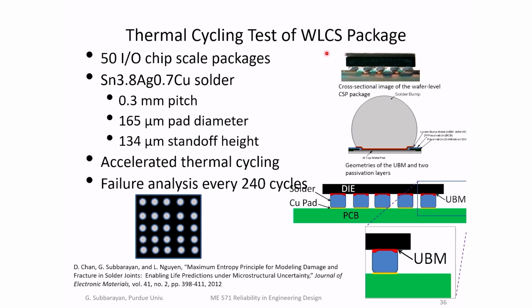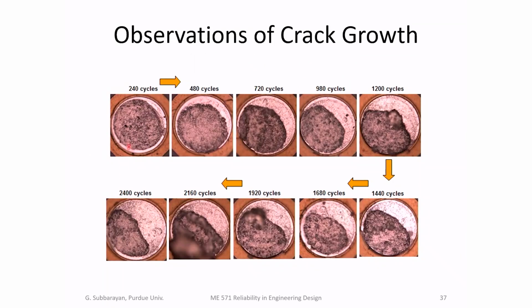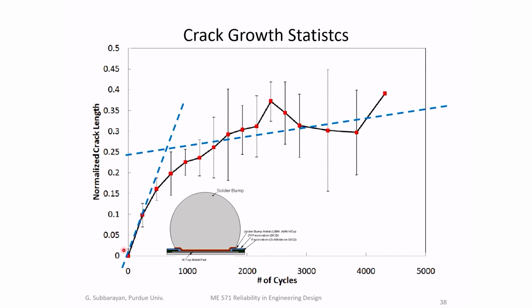So we take a wafer level chip scale package, and then we cycle them in a thermal chamber. Every 240 cycles, the test board was sent to us to do failure analysis. So we characterized how fast the cracks grew in the real sample. And this is the growth of the crack. This is how far the crack had grown at that number of cycles. You can see that the crack growth is not linear. This is the normalized crack length, and this is the number of cycles. It's highly nonlinear.